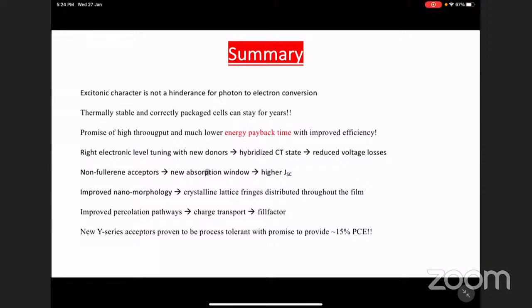Non-fullerene acceptors, additional absorption window has opened that gives the higher short circuit current densities and improved nanomorphology. The crystalline lattice fringes distributed throughout the films give you the very good fill factor and the charge transfer properties. New Y series acceptors have proven to be process tolerant with promise to provide 15% power conversion efficiency. That is very encouraging. Means today, if somebody wants to start doing research in organic solar cells, if they get PM6, Y6, within a month, they should get a 15% solar cell in their laboratory.